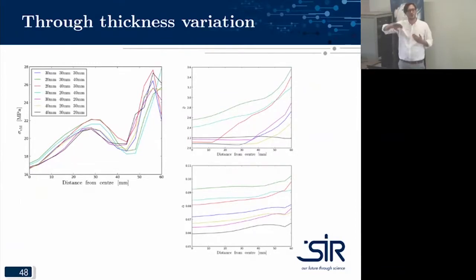So the one would be far more functionally graded, so you would expect that at the very surface of the material it's slightly harder than at the middle, whereas the other method would mean it would be fairly consistent in terms of strength throughout the material.